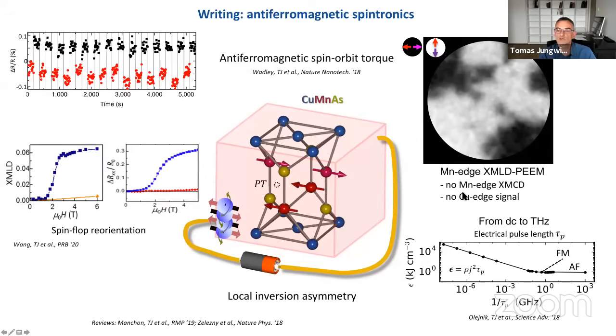In X-rays, we can also switch from manganese edge to copper edge, for example, and see if the signal that we're detecting is indeed of magnetic origin. If we saw the same signal at copper edge, we would understand that the changes are because of some structural modifications. But in this experiment, it's been verified that there is no signal on the copper edge, which again confirms that the signal is because of magnetic origin and specifically of antiferromagnetic origin.